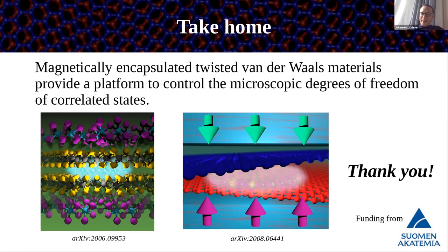Okay, that seemed to answer the question. I was also wondering about when you create these real space models, which, correct me if I'm wrong, are like a Wannierization of your k-space Hamiltonian. Is that correct? No, we kind of start with a real space model. So in the case of graphene, you essentially take the structure and you put, let's say, pz orbitals in each point where you have a carbon atom. And in the case of dichalcogenides, you essentially take some kind of honeycomb lattice in which you put both charge order and spin-orbit coupling. So you start directly from real space, let's say.